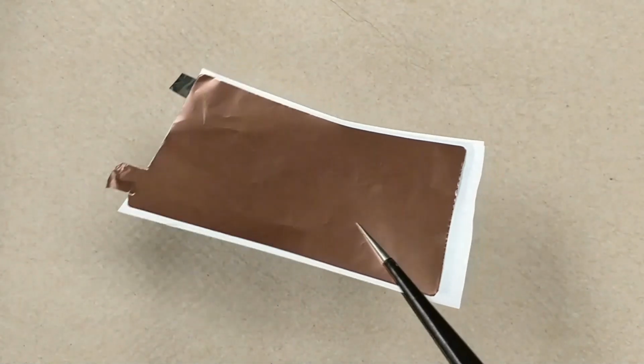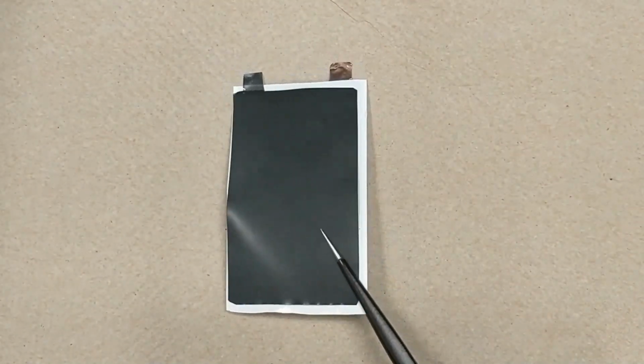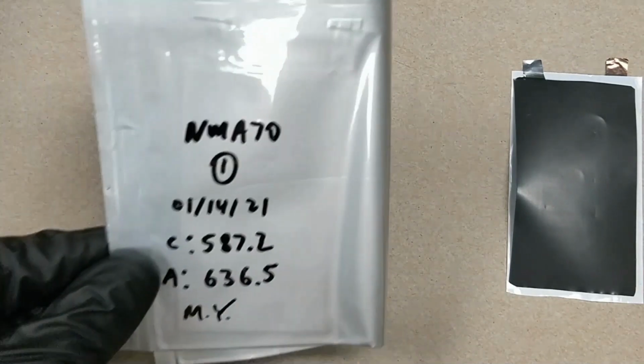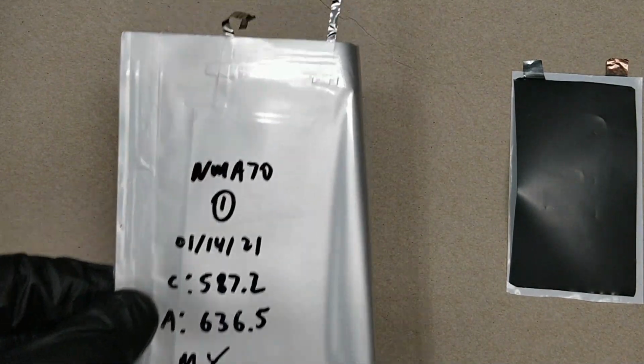Note that unlike the aluminum air fuel cell, the voltage of a single lithium-ion cell is about 4 volts. Therefore, not only a water-based electrolyte should be avoided, but also the cell components need to be protected from the ambient moisture and atmospheric gases that can undergo unwanted side reactions. In order to do this, the cell is enclosed and sealed in a protective pouch cell, such as the one shown here.